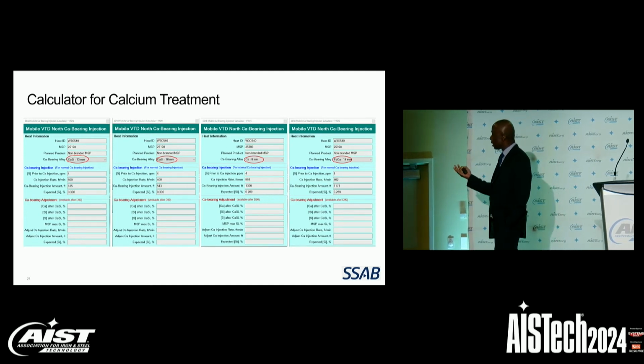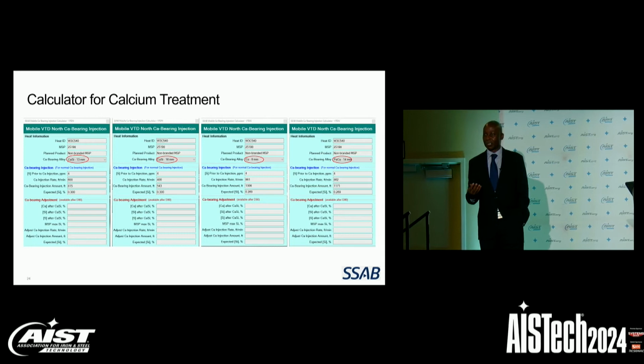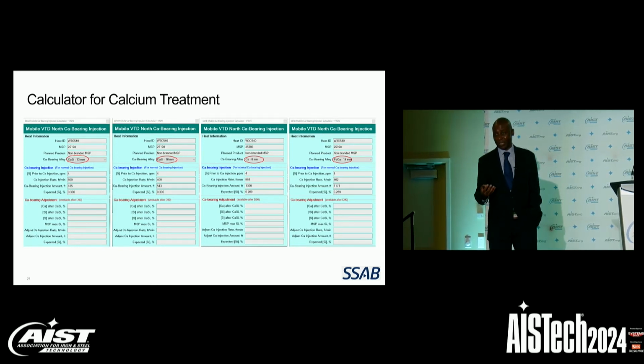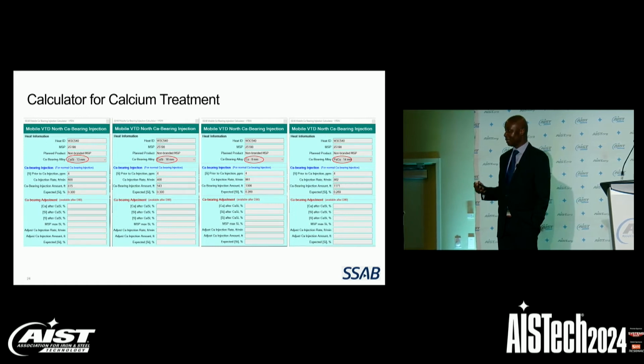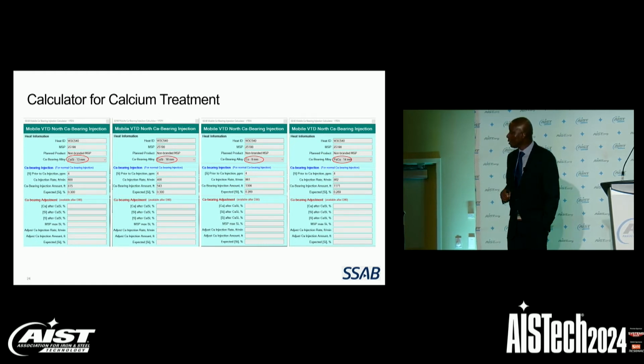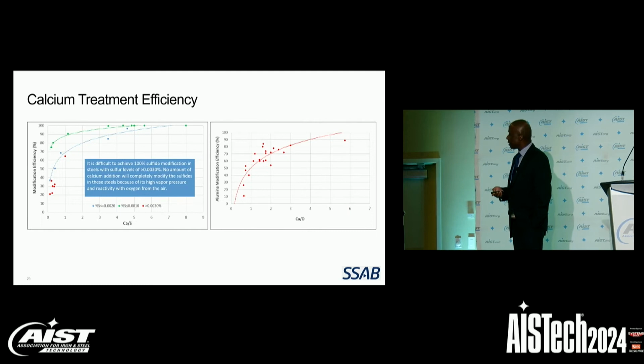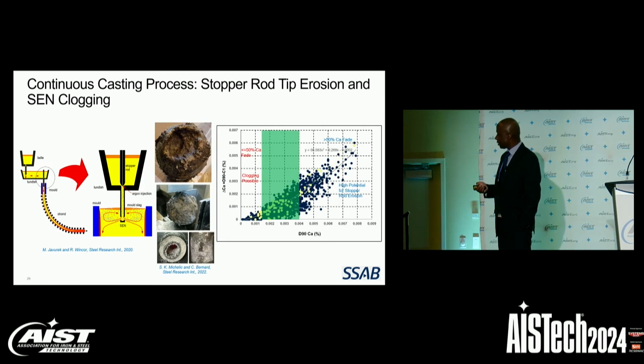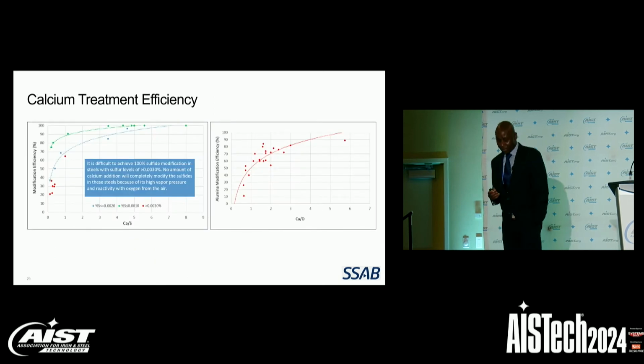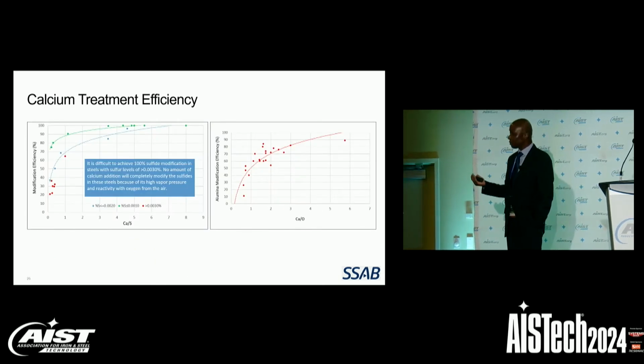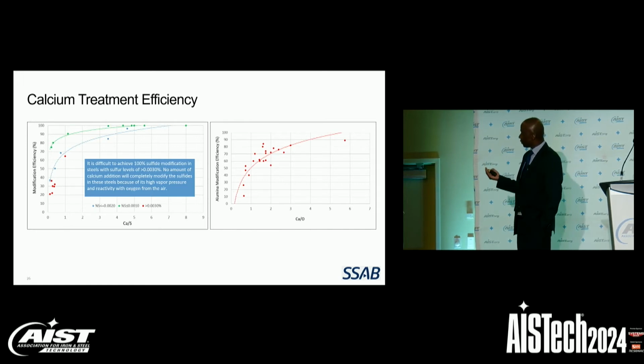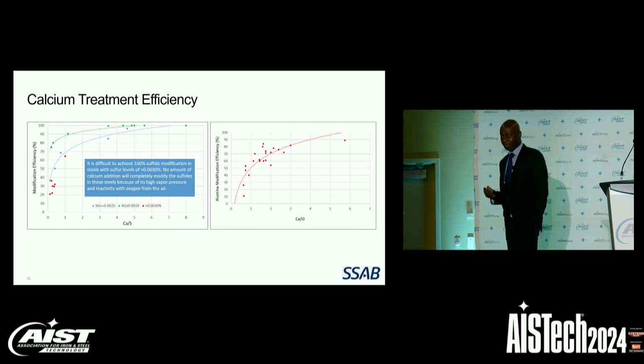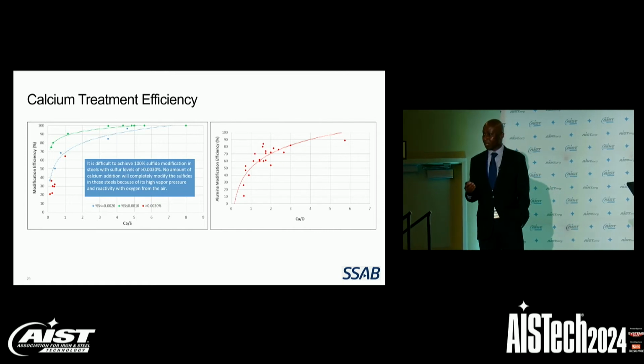So we have a calculator that, at the end of refining process, we can determine for any calcium-bearing agent how much of that material should be added to ensure that the sulfide and the alumina inclusions are efficiently modified. And what we found is that the modification efficiency of sulfides is related to the calcium to sulfur ratio, and the modification efficiency of alumina inclusions is related to the calcium to oxygen ratio.